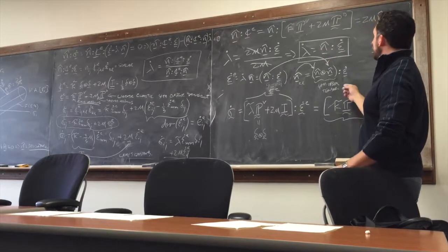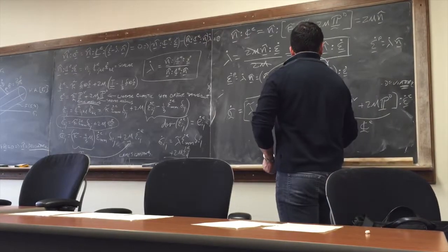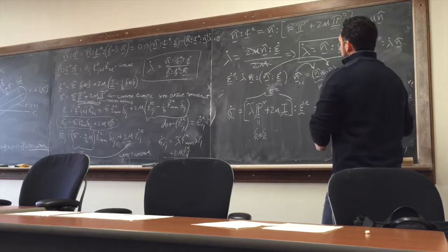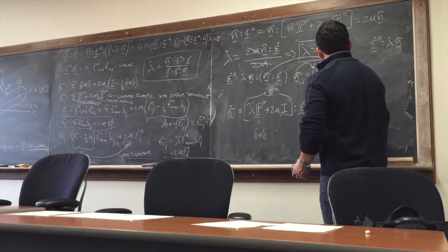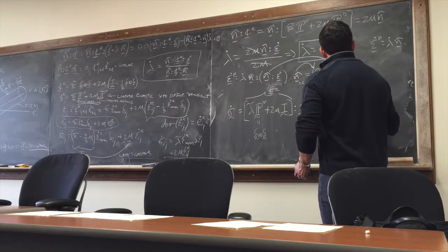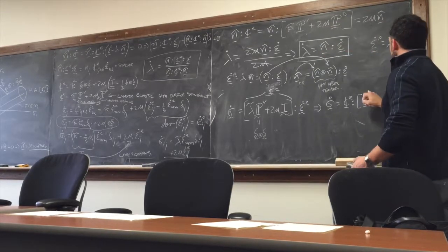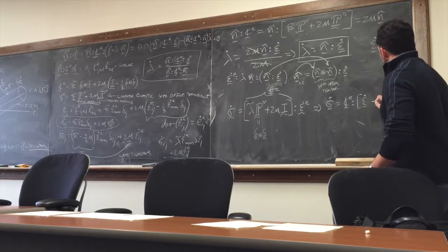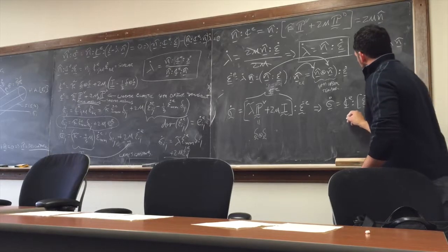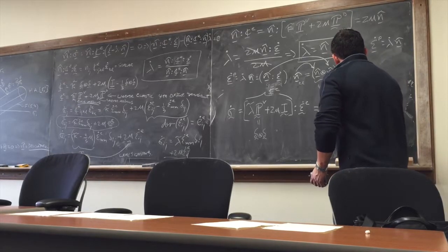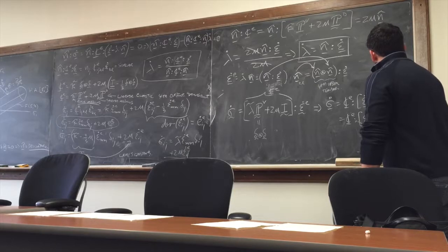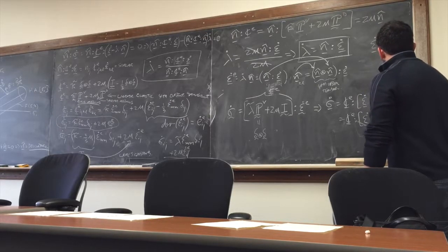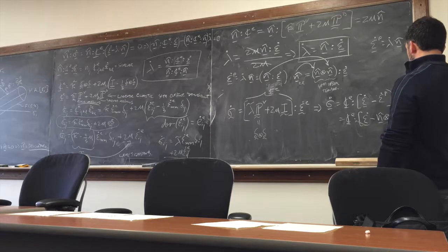And now that leaves me ready to put everything together in one final step. Because I go back to Hooke's law that says sigma dot equals C^e double contracted with epsilon dot e, which is epsilon dot minus epsilon dot p. So C^e double contracted with epsilon dot minus, I'm just going to introduce this, n hat dyad n hat, all of that double contracted. What am I doing?